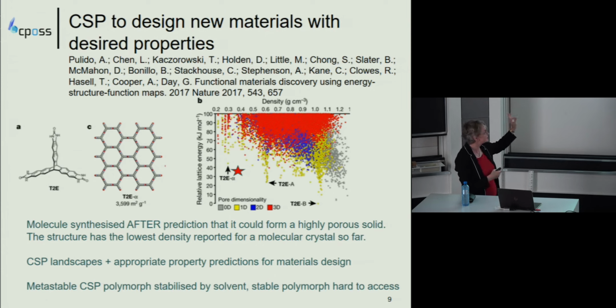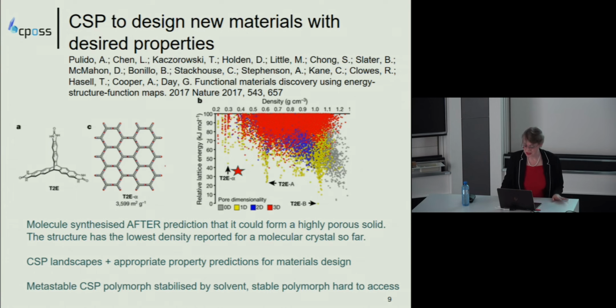It is a metastable polymorph in this crystal structure prediction, but it comes out because, of course, there's solvent there, stable in the pores, stabilizing it as it crystallizes, but you can exchange the gas or the solvent in the pores. And actually, they'd already published this in Nature before they were eventually able to crystallize the most stable polymorph, which was the lowest energy but denser structure.